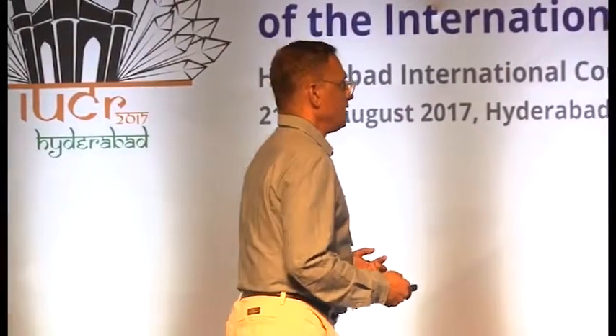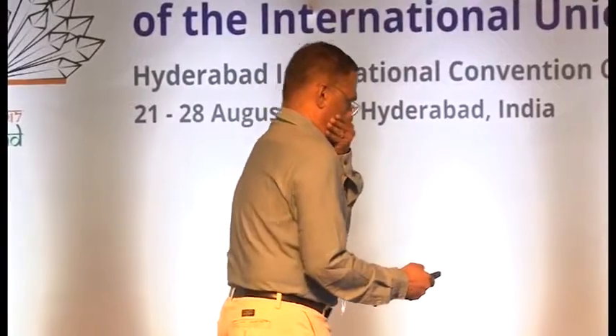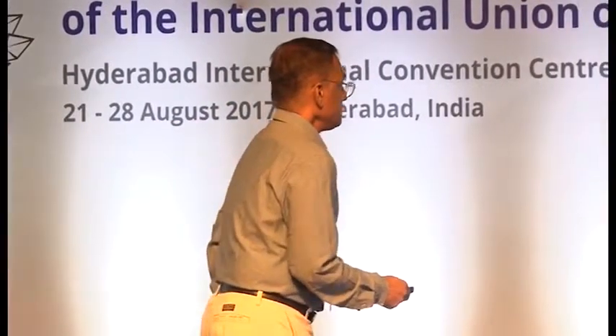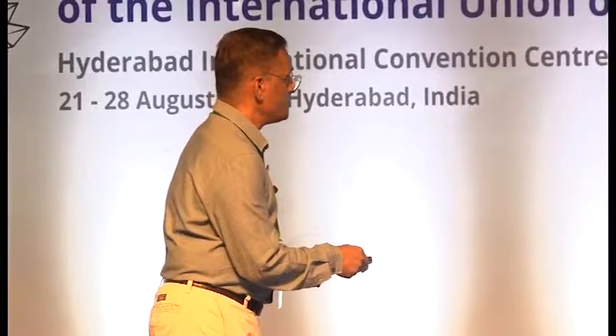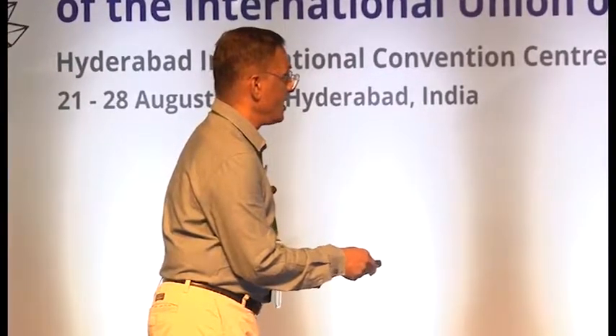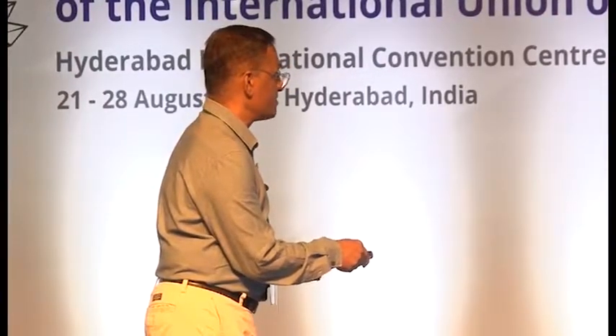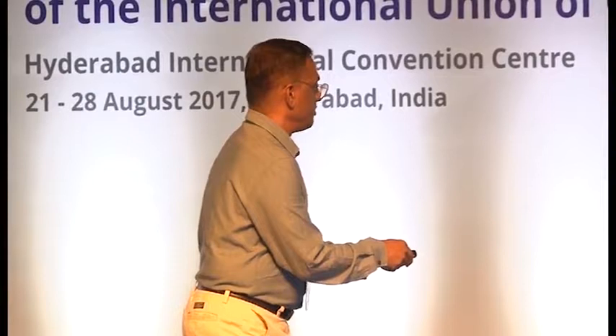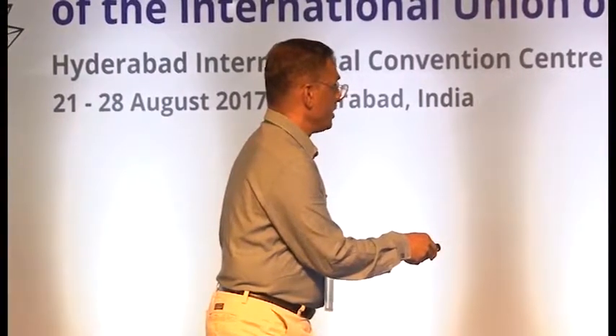When we change the substitution on 4-styrylpyridine, excuse me, it's exactly the same. Okay, this is isomorphous and isostructural to the previous compound with 4-styrylpyridine. This is also a dimer. Only thing is you have an extra fluorine that is bonded to it. Again, on one side of it, you have parallel orientation of the olefin bonds. On the other side, it is slightly slip-stacked. And you see this, the double bond from the fluorophenyl group is closely aligned to the double bonds of the olefin here.